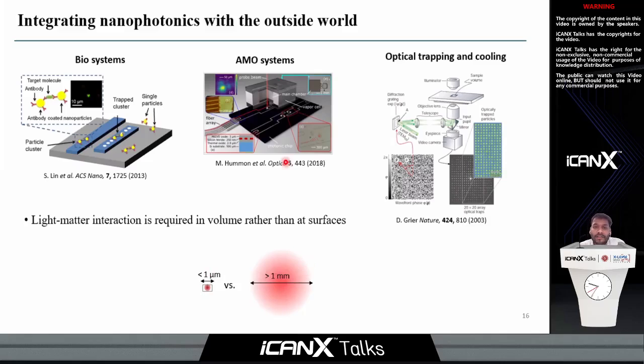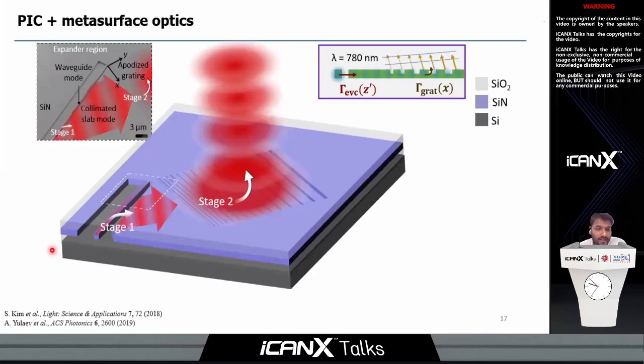And so how does one use the best of both worlds, which is what free-space optics gives us, but also the manufacturability aspect of, say, integrated photonics? This was addressed in a series of papers that came out together with Vladimir Aksyuk's group here at NIST, in a collaboration where they showed this extreme mode converter platform. If I have light in a waveguide and I want to come out of the chip with a decent beam diameter, then what you do is a one-dimensional light leakage into the slab mode of the waveguide.